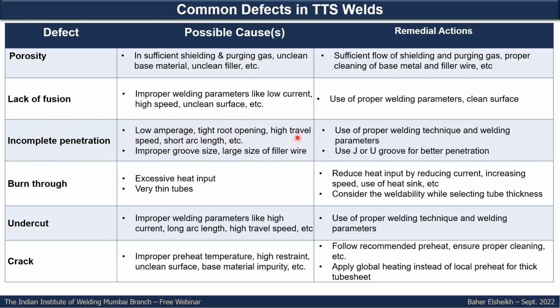For incomplete penetration, control the weld parameters itself, or from the design perspective have a proper groove size or groove shape, so you have a better chance of achieving good penetration. Also select a smaller filler wire size for proper penetration during the root pass. Burn through can be seen in thin tubes in some applications, and you need to control the heat input to avoid that. Undercut is caused by high current or long arc length, so use the proper welding technique and parameters. That's why, if you qualify the WPS by a mock-up, you can fix all the parameters like that.